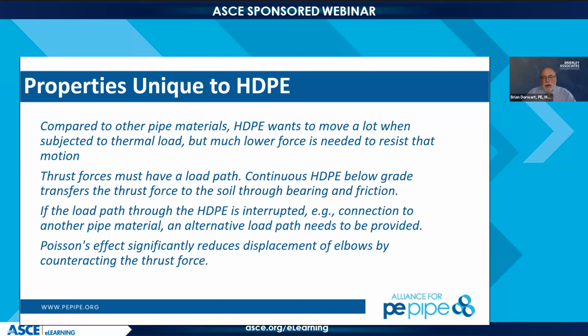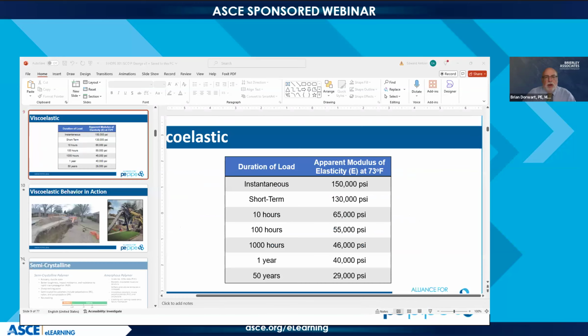Well, if this is installed in an open trench and then backfilled and compacted, there's really not a lot of change on the strength. It's going to pretty much stay fairly constant, and the soil is going to have enough resistance in it that even if you were to assume a fairly long frictional debonding, that strength is really not going to be exceeded. And you have to look at it in terms of stress and strain and strength. They're all interrelated. Well, if that pipe shrinks, it's going to create strain in the pipe, which is going to create a stress, which is your thrust restraint or your anchorage restraint value. So does that really change?